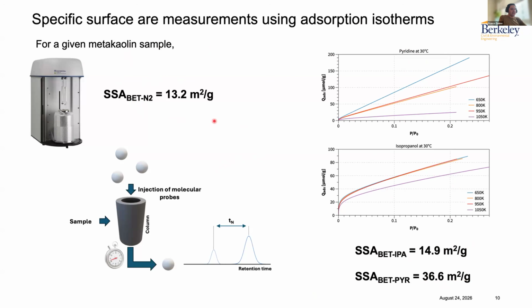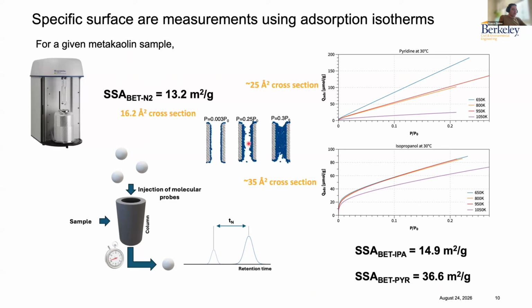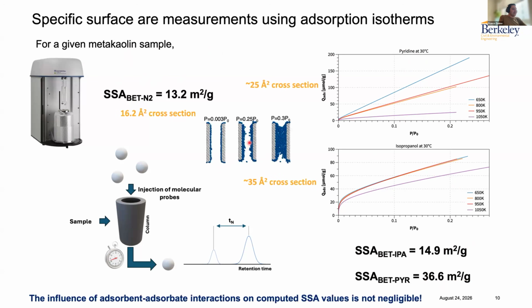So in a sense, we cannot neglect the influence or the interaction between the adsorbate and the adsorbent in this analysis, because while the assumption for nitrogen may stand true for classical cementitious materials, in many cases, the chemistry of the surfaces of these emerging SCMs is such that those interactions cannot be neglected anymore.